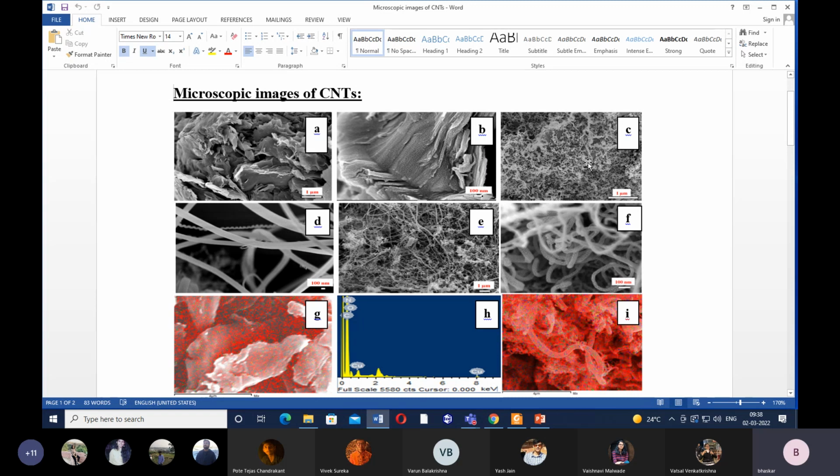Remember this. With your naked eyes, you cannot see this morphology. Whenever I have the material ready, I put it under the microscope and grab these images. So these are for the pure graphite powder, and after that, I had dispersion of copper nanoparticles on the graphite powder. Then I allowed C2H2 to come in contact with the copper-doped surface at a temperature of around 350 degrees Celsius for 30 minutes. Now you can ask me, why did you select the temperature to be 350, and why did you carry out the reaction for a period of 30 minutes?